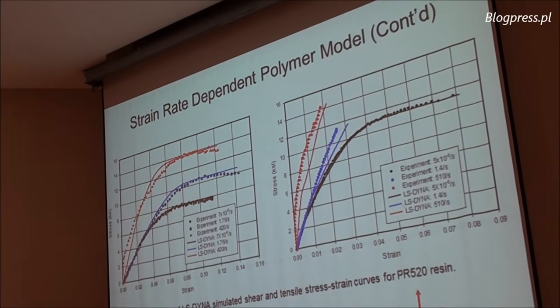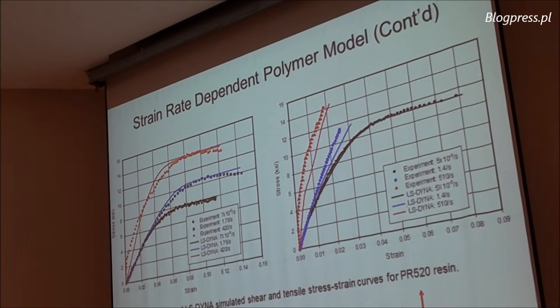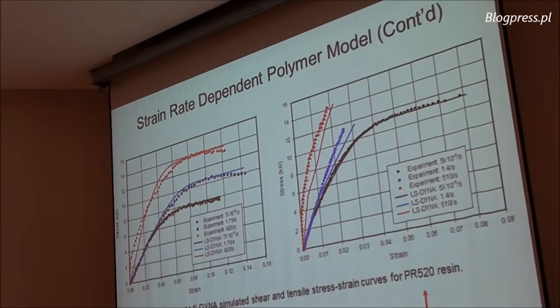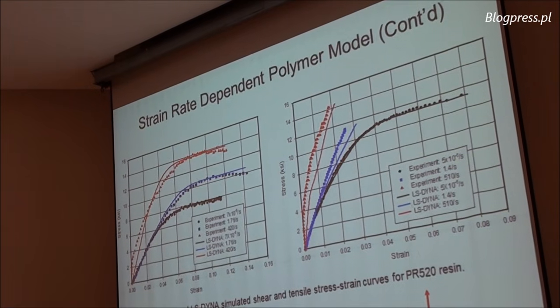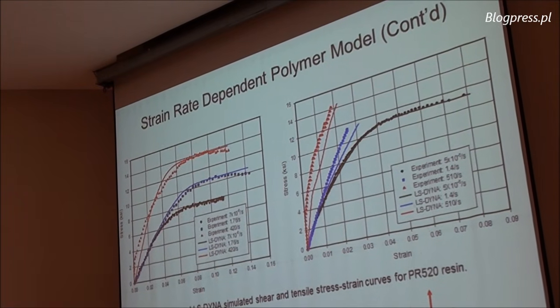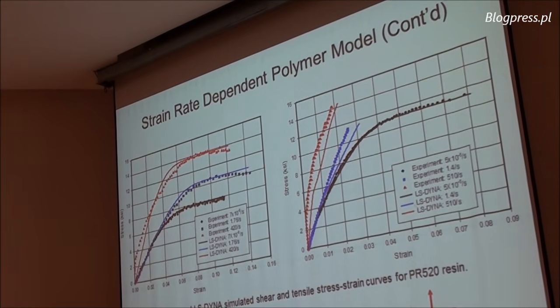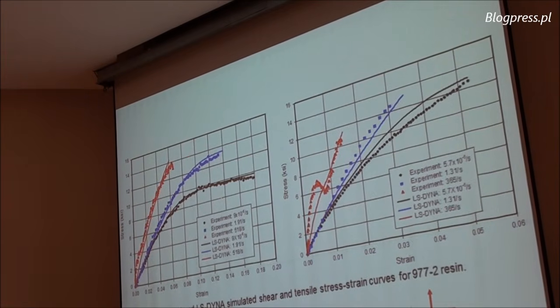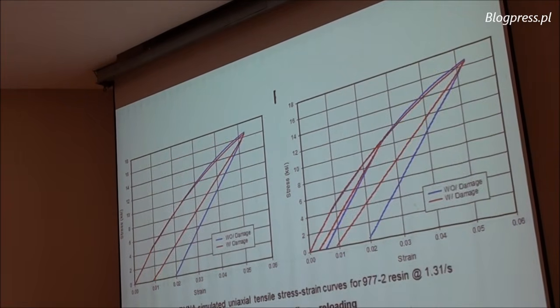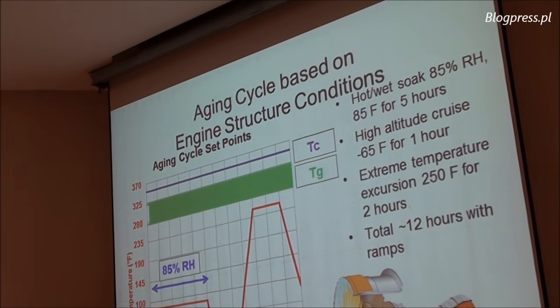And we developed a UMAT for LS-DYNA, which is basically a system of steps that will incorporate this model into the finite element calculations. And the bottom line is to have experimental data and simulations, and convince yourself that yes, you capture the behavior of this material at different strain rates, and then you can move on to the next step of the analysis.